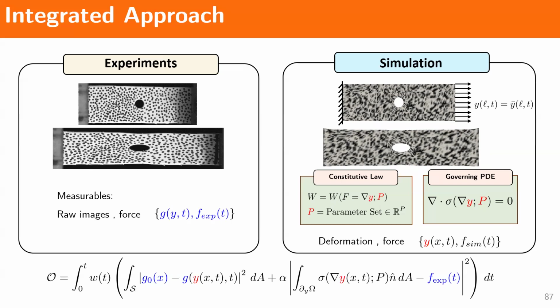So really the important thing here that I want to highlight is, if you notice, the displacement field that we get here already satisfies our governing PDE. So this displacement field already satisfies equilibrium and compatibility. And so this is different from the current established approach, because in trying to minimize this objective, we're looking over all possible material parameters P here, while already restricting ourselves to the displacement field that already comes from our P. So the displacement field here already has to satisfy our governing PDE.